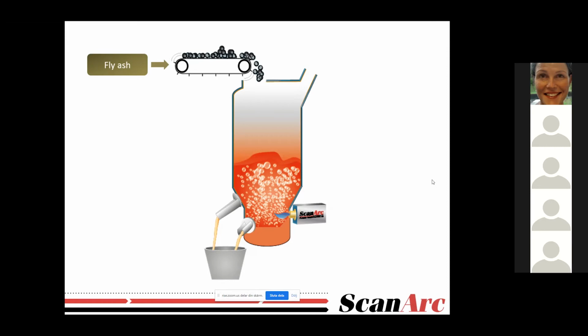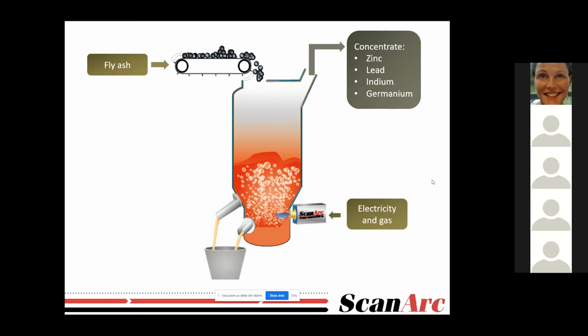Energy is then supplied at the bottom, where we use electricity. We inject gas. And then we inject the hot gas here at the bottom. Some of the metals that we now have in this molten bath have a tendency to fume at a very high temperature, and zinc and lead are among those. And now for some reason I have also used indium and germanium, which may not be present in the fly ash. But these are metals, along with silver, I could also have included, that behave equally under these circumstances, that when they are exposed to this very high temperature and the atmosphere that we create, these will fume and evaporate, and we collect them in a filter. So these metals are concentrated in a filter product, and with the very high concentrations of these metals, this is a valuable product with an existing market, just as Karin talked about in her presentation.